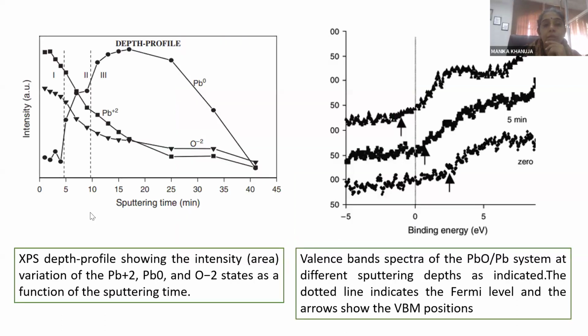Yes, it's here. So in this XPS depth profile of the first region, second region, third region, this Pb+2 signal is falling, because Pb+2 is only in the shell. If you keep on removing the outer part, keep on slicing, finally this Pb+2 signal declines, and the Pb0 signal, which is the core signal, will keep on emerging. So you see the Pb+2 signal keeps on declining, and the Pb0 signal keeps on rising. And if the Pb+2 signal declines, it means the oxygen signal also declines, because Pb+2 means lead oxide. So you see this oxide core level also follows the Pb+2, just mimics the Pb+2.